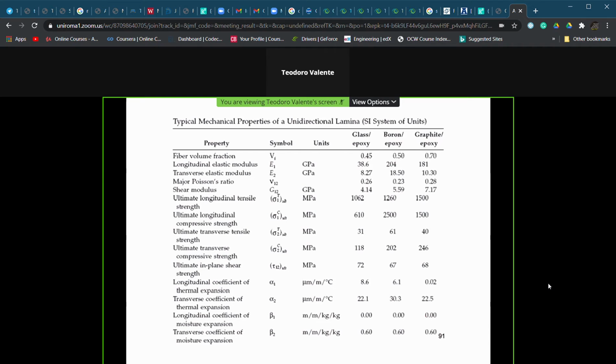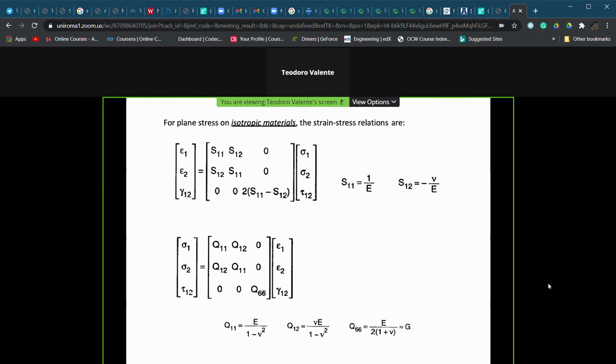micro-mechanical approach. Here you have some values, just for some special conditions, but just to have an idea for different systems. For example, for glass epoxy with 45% fiber volume fraction, or boron epoxy, or graphite epoxy, you see they are all polymeric matrix composites, in terms of modulus and in terms of other properties, like, for example, thermal expansion coefficient or coefficient of moisture expansion. That's very important for a unidirectional lamina. Okay, just to have some figures, just to have an idea.